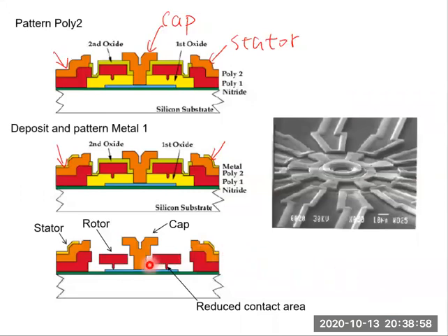Finally, the polysilicon micromotor is released in HF. So the oxide layers, the two PSG layers, are removed by HF. And the rotor now becomes freestanding after sacrificial layer etching. And it is constrained by this cap, right? So it can only rotate, okay? This rotor can only rotate, no translational movement.